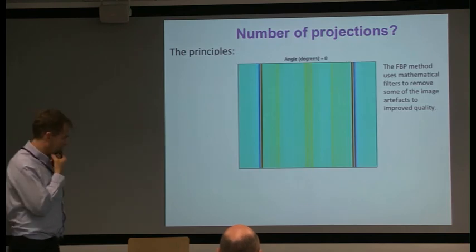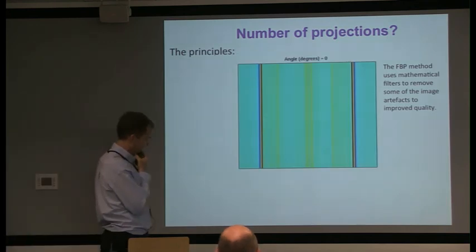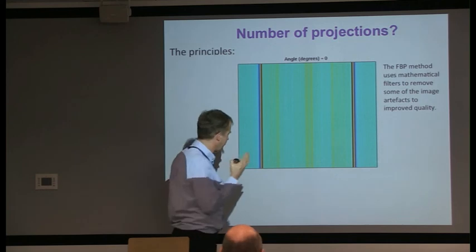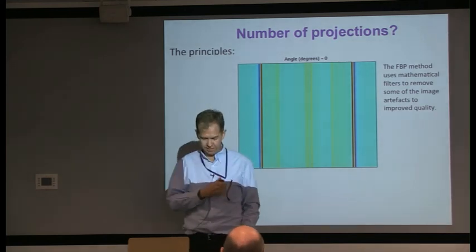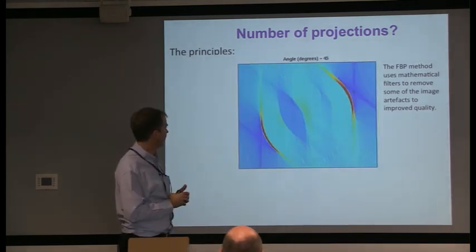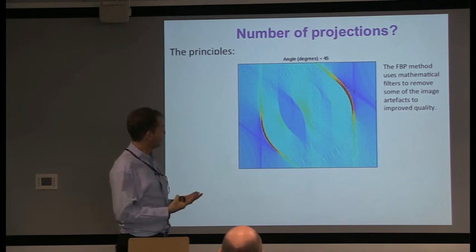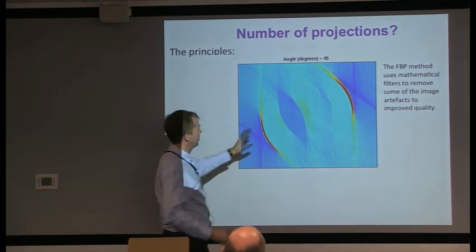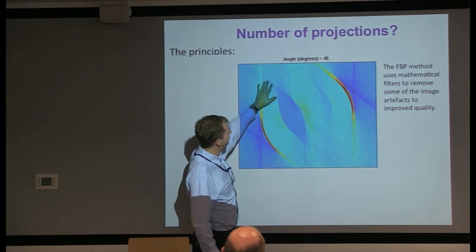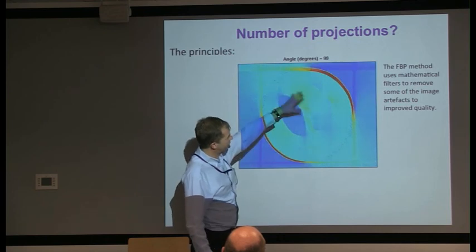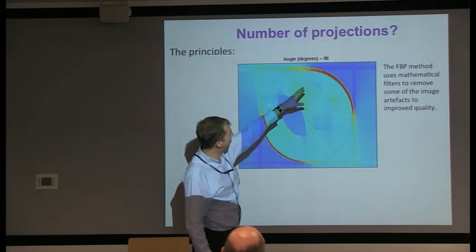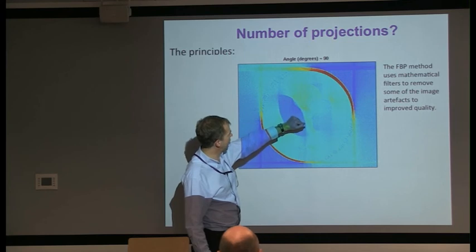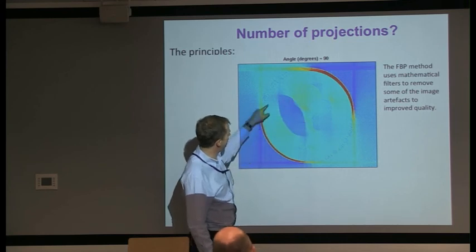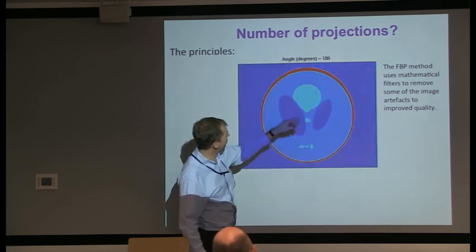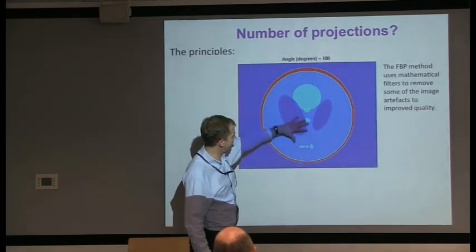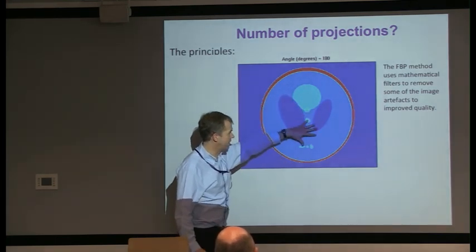The other thing to think about is time. If you're looking at a fast process, you need to integrate up these projections as you're doing it. It's very simple - the resolution goes up with 1 over the square root of the number of projections. As I add angle and degree, going from 45 to 90 projections, you can start seeing something resolved, and as I go through I can now see what my original phantom or shape is within it.